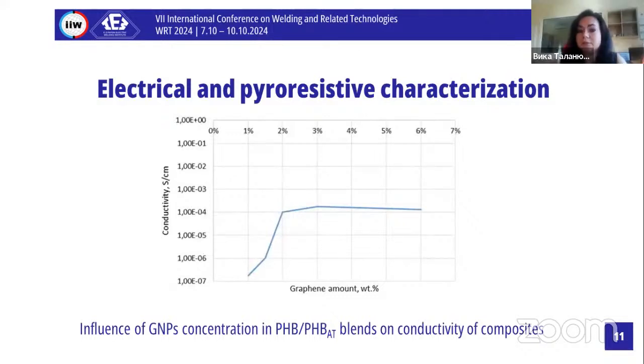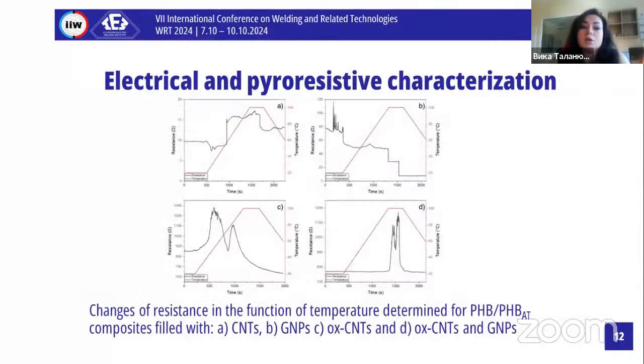What we get in the end of our measurements with these materials, the main thing we need to get is the electrical properties for the pyroresistive characterization. In this picture, you can see that we use not just different kinds of fillers, but different concentrations of fillers. We start with GNP, and we see that the optimal concentration of the mass is 2%, because the other steps change our conductivity properties a little bit, and the optimal of our measurements shows which of these samples we need to choose. We tried from 0.5 to 6% of the mass, but we chose 2% as the best for the fillers. Our electrical pyroresistive characterization shows us how we get different kinds of fillers.